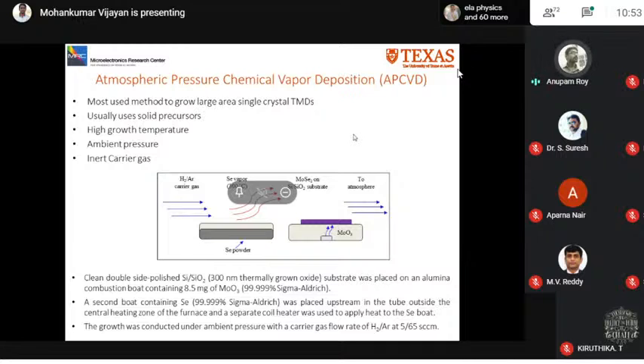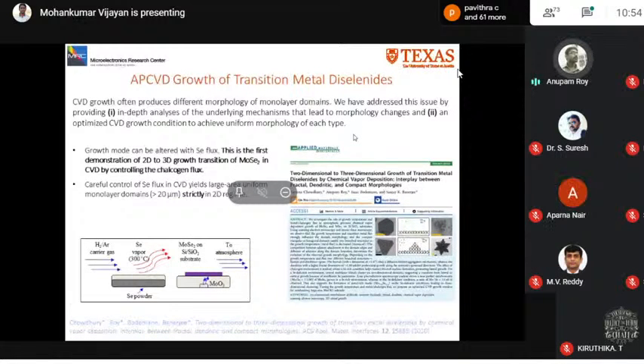As seen in the schematic here, the growth substrate is placed face down on an alumina crucible that contains the metal oxide powder. The chalcogen powder is placed in the upstream region away from the central heating zone and heated using a separate coil heater. And an inert carrier gas, usually hydrogen and argon, is used. That usually carries the precursor to the growth substrate and carries the reaction products out of the system via the exhaust. So in the next slide, I'll focus on this.